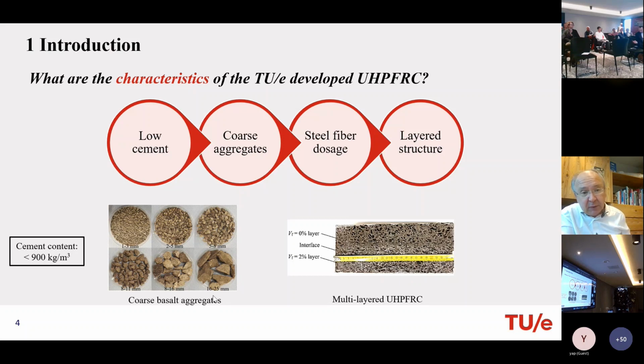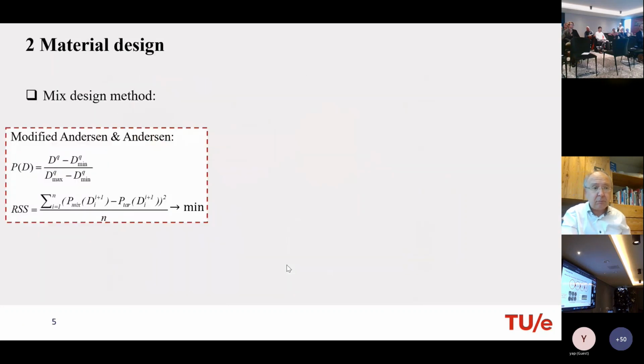We use aggregates. Well, the aggregates must also be of high strength. Of course, you cannot use quartz aggregates. So we use basalt aggregates for these ultra high performance concretes. And we use them in all kinds of gradations. And here you can see the sand size, 1 to 3 millimeter. But we even went to 16 to 25 millimeter aggregates.